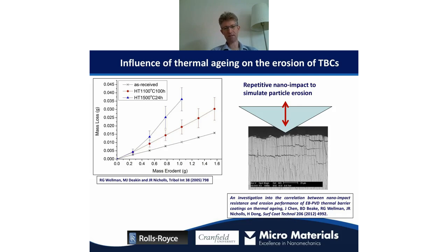What you can see here is that this material here, this columnar thermal barrier coating, is being eroded away essentially as a function of time here. But when you thermally age it, it's being eroded away more quickly, and particularly at this higher temperature of 1500 degrees. So the shorter exposure for the high temperature is even worse. So this is potentially problematic. It influences how often these things need to be checked and serviced. So we want to try and understand these things and design materials with better life.